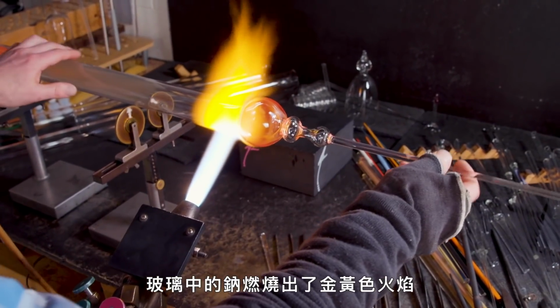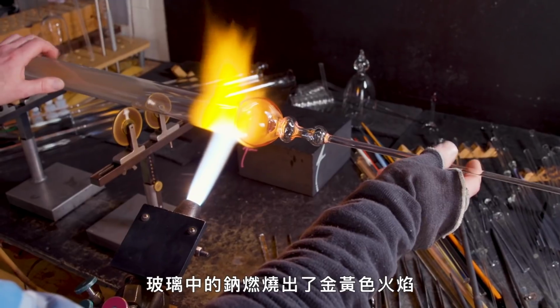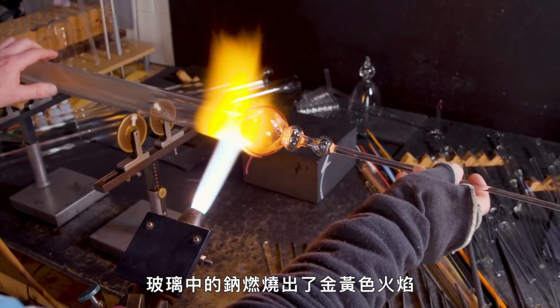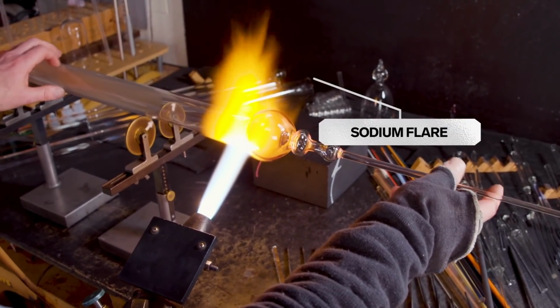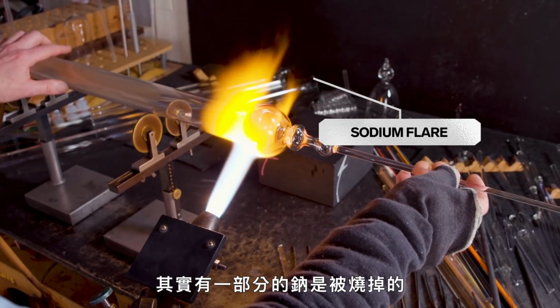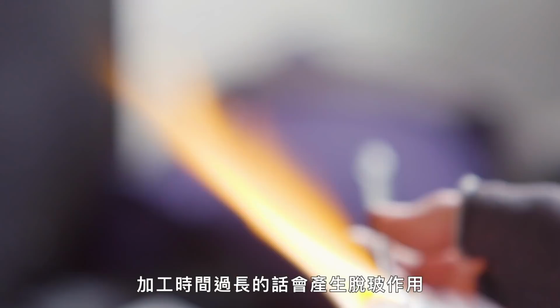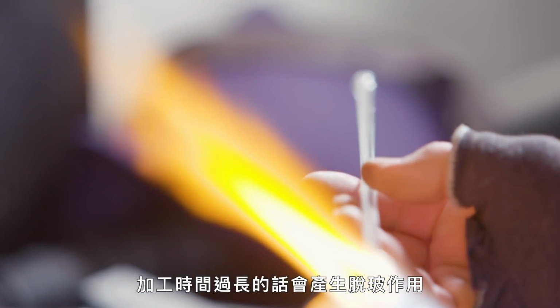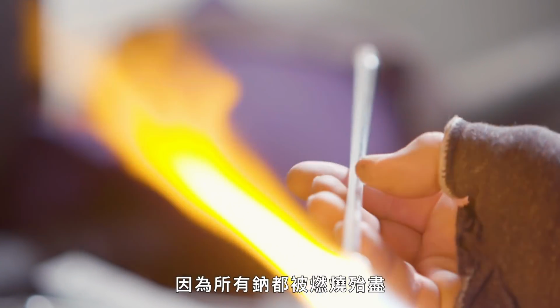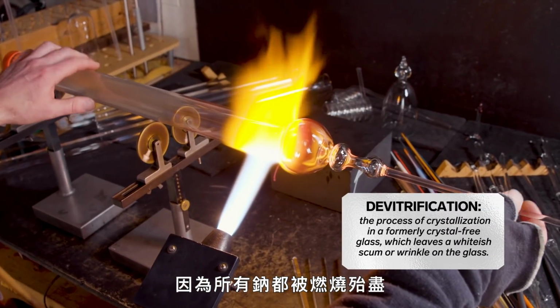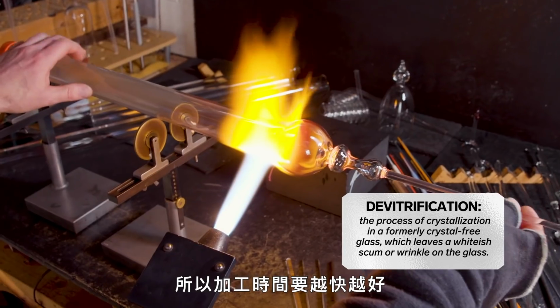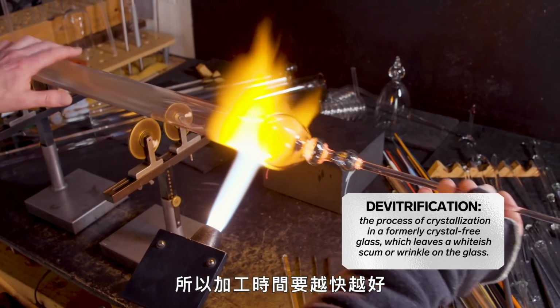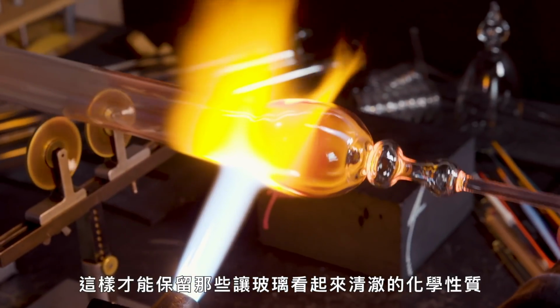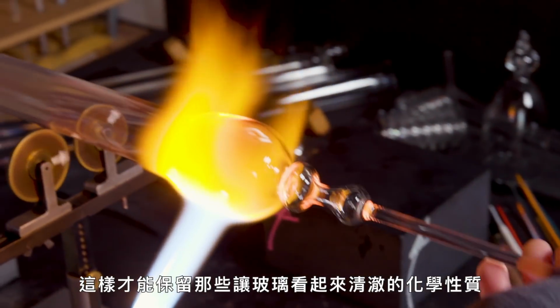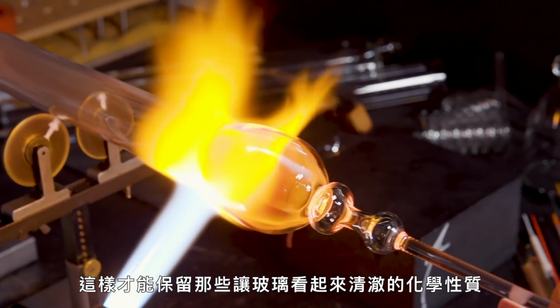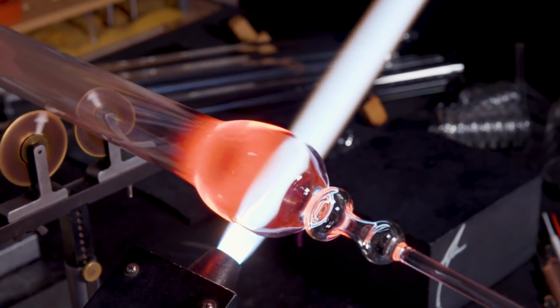The sodium that's in the glass is what's burning off. That's the bright yellow you see. It's called a sodium flare. So the glass is actually giving some of its life away. Overworking the glass can cause devitrification because you burn all of the sodium out. So you want to try to work the glass as little as possible so that you maintain the integrity and the chemical properties in the glass that you need to keep it clear.